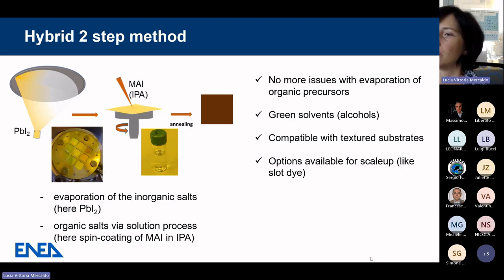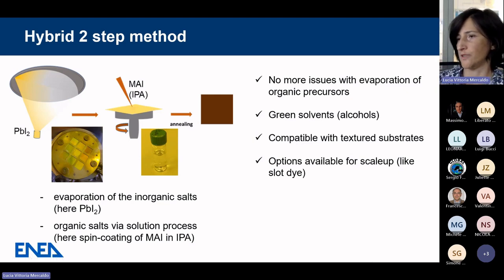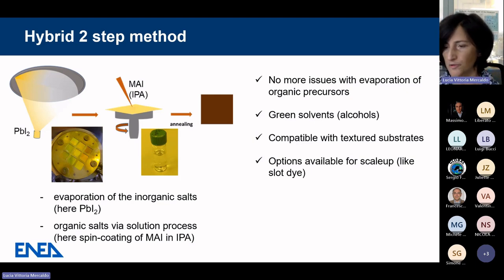With this approach, there are no more issues with the evaporation of the organic precursors. This is an advantage. We can still use green solvents, so it's okay for the environment. Still, the compatibility with textured substrates is maintained. And as for the scale-up, there are options available. Of course, not spin coating, but from spin coating, one could move, for example, to slot die.